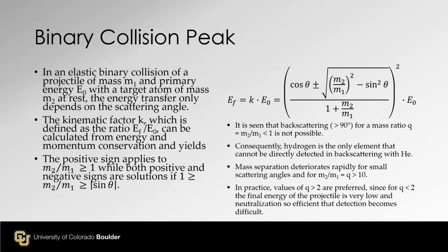Okay, so you can ignore many things. Look at the equation, E final. It only depends on M1, the primary ion. M2, mass 2, is the target atom at rest. The final energy after the elastic collision will depend only on theta, the angle of scattering, as well as